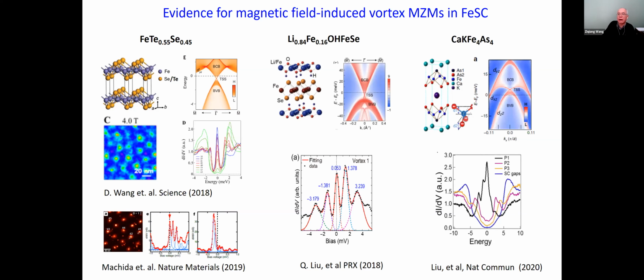And it's even in the pnictides. Again, this is also something I think, is it Vidya? Or no, the first talk this morning also mentioned this pnictides, this 1144, which is a bilayer iron pnictide that has surface states. And very recently, they have observed also this zero energy bound state in the vortex core. So all of these are actually, so far, the criteria, which is a poor criteria, but it certainly is the first criteria, the first step is to see the zero energy bound state in STM.